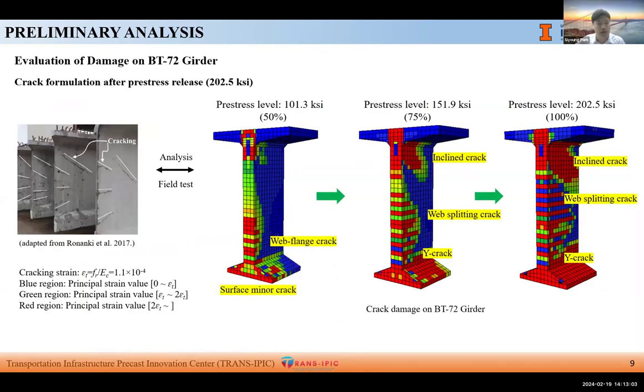Now, to evaluate the damage on BT72 girder, the maximum principal strain of the end region was analyzed after pre-stress release. Red areas are those which are thought to be fully cracked. This was set based on the value of twice of the cracking strain, which was calculated also based on the ACI. As the pre-stress level increased, we can see that crack regions are developing in web and flange areas.